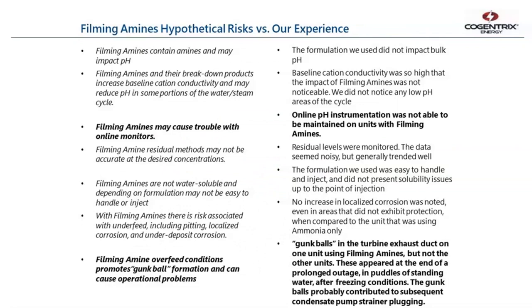There's a list of hypothetical risks of using amine based filming products, and I just wanted to highlight, because most of the scares that you might have didn't come to fruition, here's what did happen to us. People say filming amines may cause trouble with online monitors, and we did see an effect on online pH instrumentation, as you saw in the earlier slide with chemistry. The pH doesn't match the conductivity, and we never could get it to after we started using the filming amines.